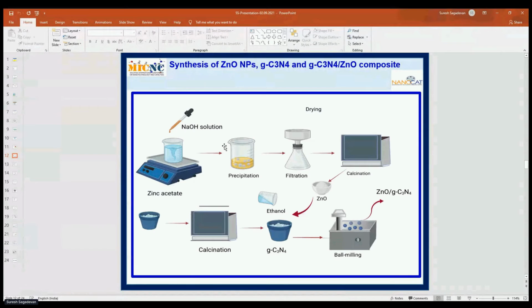For the formation of graphitic carbon nitride with zinc oxide composite, we took an equal amount, 1 gram, of both graphitic carbon nitride and zinc oxide and mixed them thoroughly using the ball milling technique with ethanol as a solvent for about 1 hour, so as to obtain an excellent talc-like product. Finally, the mixture is collected and dried in an oven at 80 to 100 degrees Celsius to remove the alcohol, where the formation of the composite is confirmed by the yellowish white product. So finally, we obtain this graphitic carbon nitride zinc oxide composite.